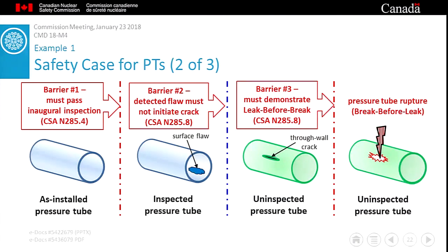This slide illustrates the progression of steps between initiation of a pressure tube flaw and a potential small break loss of coolant accident. Through careful consideration of this progression, CNSC staff has devised a series of regulatory barriers. Should a licensee wish to begin and continue to operate a pressure tube, each of these barriers must be successfully traversed. Each of the barriers has established acceptance criteria defined by the compliance verification criteria in the LCH.